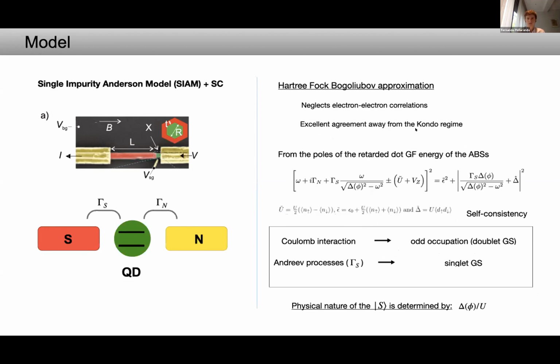So a full treatment of the problem in principle requires taking into account electron-electron correlations. However, the Coulomb blockade regime is well captured by means of a Hartree-Fock-Bogoliubov approximation, which, as we will see, provides a good agreement with the experimental data away from the Kondo regime. So from the poles of the retarded Green's functions, we can derive the energy of the Andreev bound states, which reads like this. And note here that all tilde quantities must be determined self-consistently because they depend on the occupation of the dot levels. So despite its simplicity, this model correctly captures the interplay between two competing mechanisms, which are the Coulomb interaction that favors an odd occupation in the dot with a doublet ground state, and Andreev processes that favor, on the other hand, a singlet ground state, whose physical nature will depend on the ratio of delta over U, as we will see.